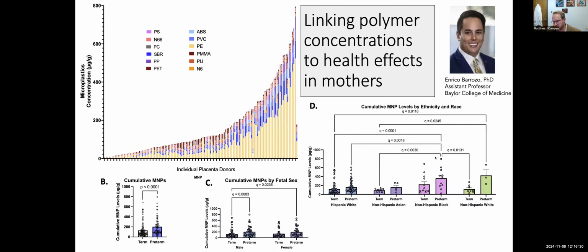The important thing of doing this and having this method is that now we can link concentrations of plastics to health outcomes. This is our first endeavor with this, working with Enrico Barozzo from Baylor College of Medicine. If you look down in the lower left-hand corner at B, this is looking at the cumulative amount of plastics as we measure with this assay and comparing placentas from term versus preterm. You can see that there tends to be higher concentrations of plastics in the preterm placenta, which is impressive given that preterm, by definition, is about 3 or 4 weeks younger than the term placentas. So there's a greater amount of accumulation in those. Whether that's cause or effect, we can't say. We also see some differences between ethnicity and race in these populations, with non-Hispanic black and non-Hispanic white mothers having higher concentrations in the placenta, both at term and preterm.